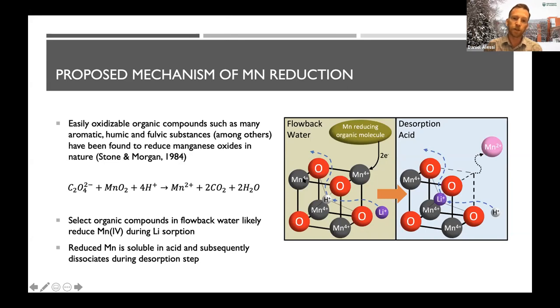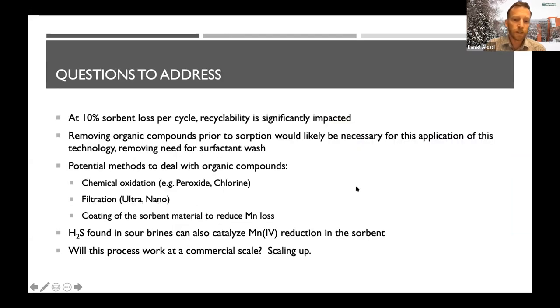So this is the problem in a nutshell, and this is what, in at least the manganese-based sorbents, people are trying to deal with to make this process economic. So yeah, the first point's obviously we said it many times, but at 9-10% sorbent loss per cycle, even really 2-3%, it's not going to stand up for the 100 to 150 cycles that we need.